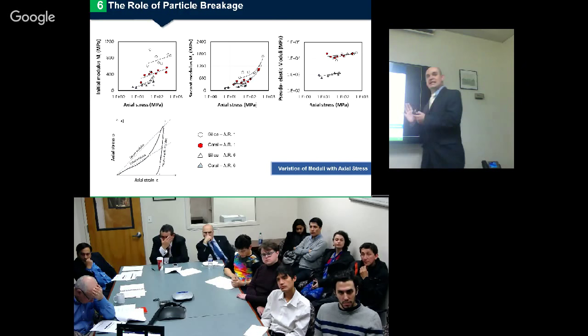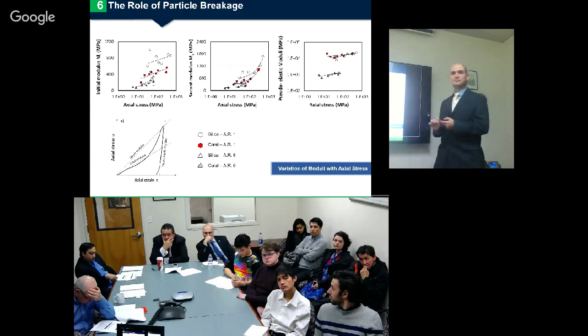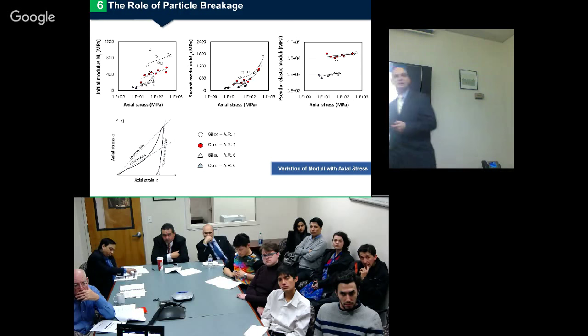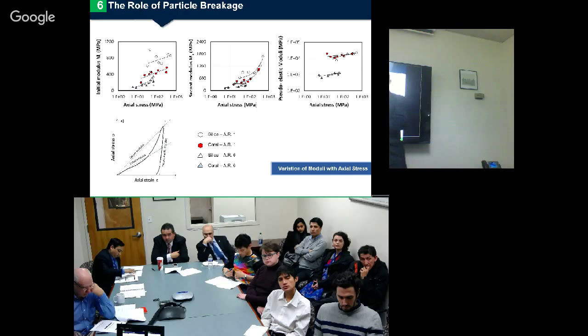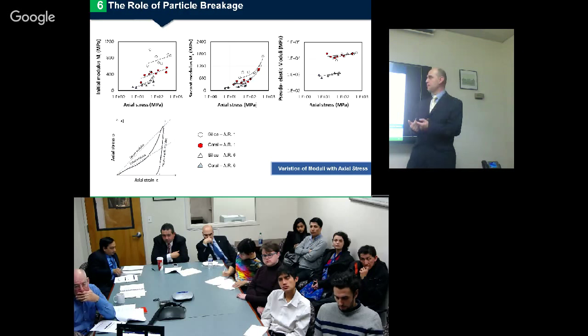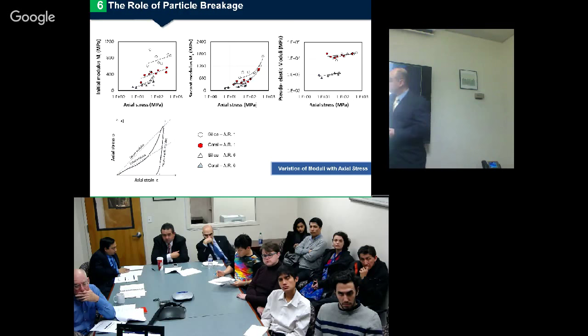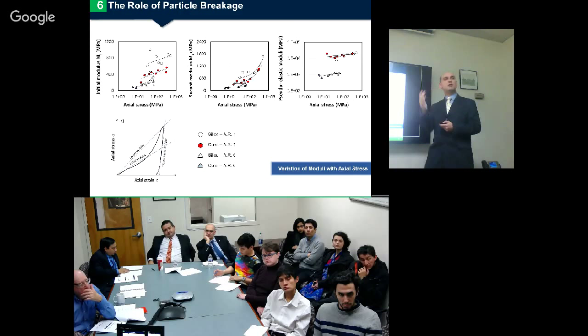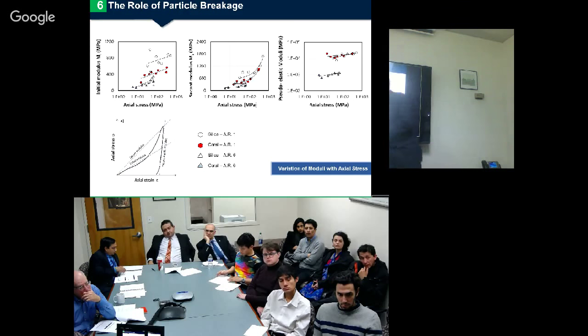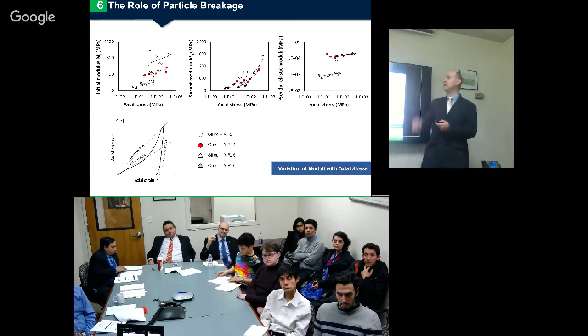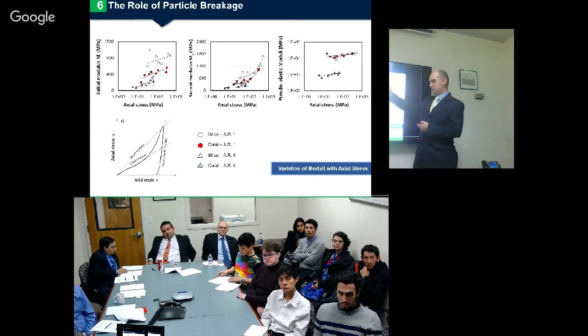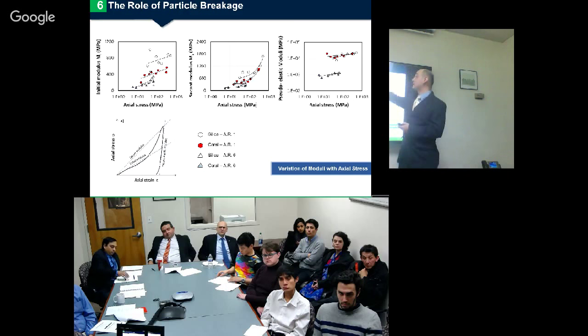We also have a similar behavior of this uniaxial loading and unloading, but instead of axial deformation, we have axial stresses. So what's the idea? Again, initial moduli, which is the first part of the curve, the secant moduli, and the pseudoelastic or elasticity moduli measured in the loading curve. Obviously, a slight increase, due to the strain rate condition, as we saw initially. The secant moduli of these two materials, silica and coral sand, with aspect ratio of 1, will increase after some point, after like 100 megapascals is reached.